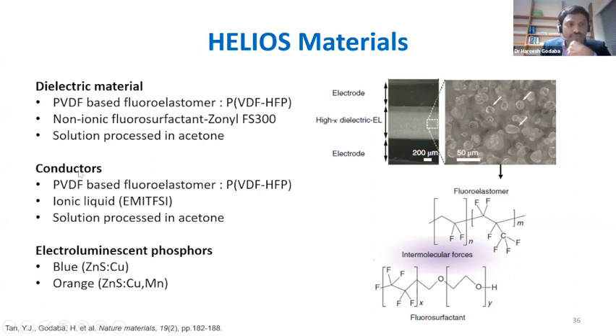Then for the conductor, or the conductive layer, which we name the electrode, we use the same base material, PVDF HFP. But instead of this non-ionic fluorosurfactant, to make it conductive, we use an ionic liquid. And as an interesting byproduct, what we found is that this ionic liquid also helps to make this conductor self-healing. So the ionic liquid also has some surfactant type properties which make this conductor self-healing. And this is also solution processed in acetone.